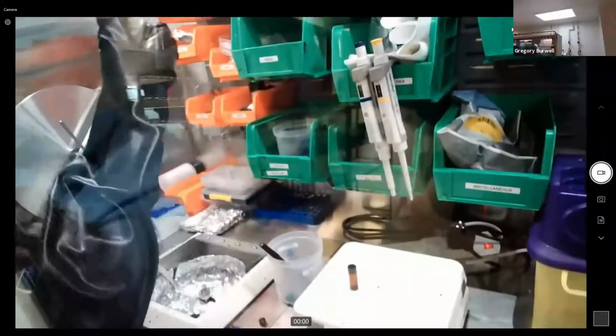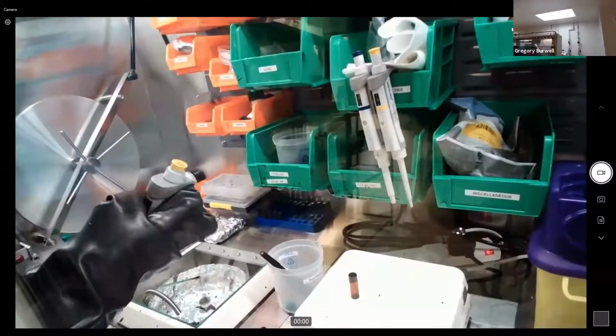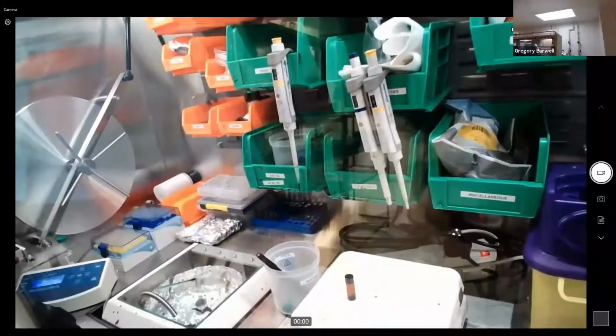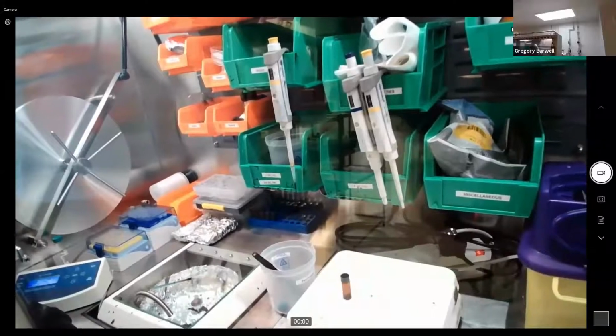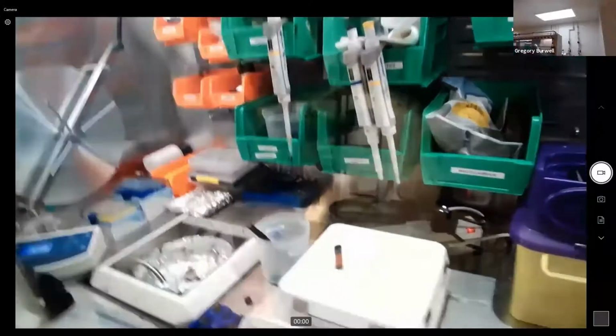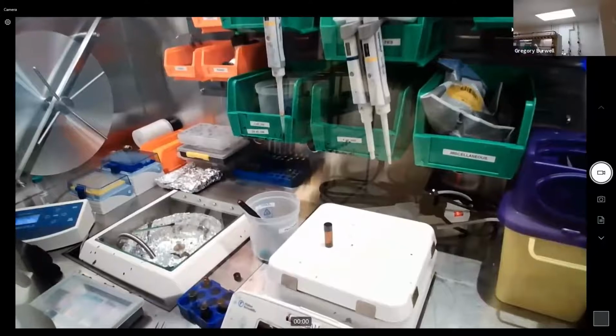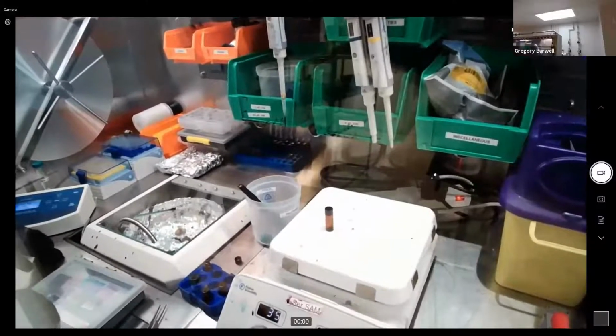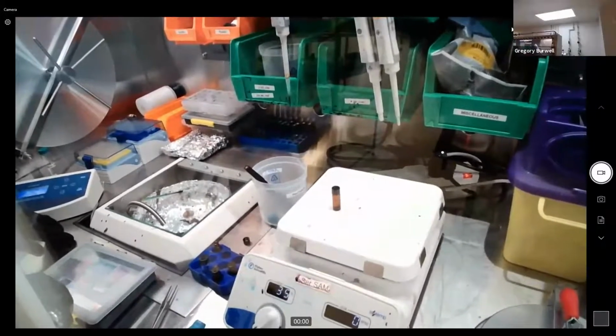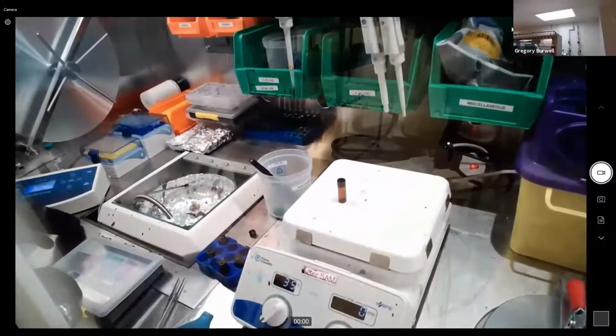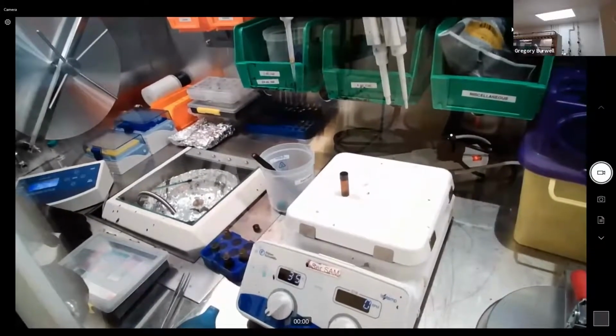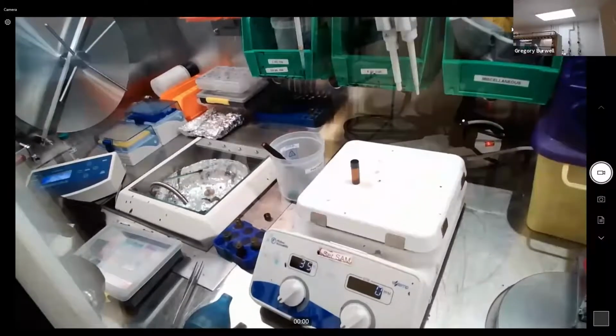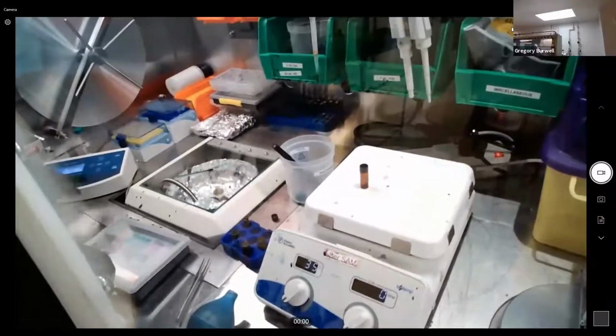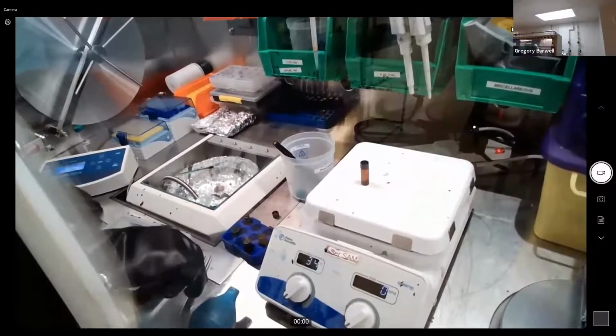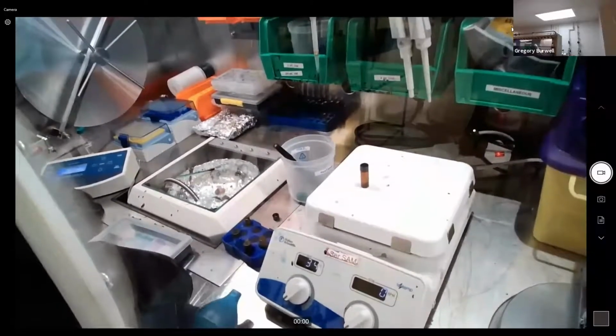So you should be able to see Wei casting a film now onto the substrate. And now we're spinning, and now you can see as it's spinning, it's coating the whole substrate quite evenly. This class of materials we call solution processable. So spin coating is one technique we use, particularly in research and development like this, but there's other ways of coating substrates with thin films, such as blade coating, that might be more suitable for larger areas. And it can be as quick as that. So when it's finished spinning, I think Wei will give us a look.